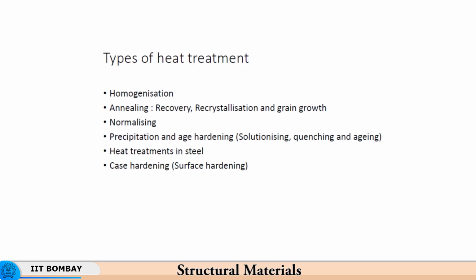So, what people do is, people often work the material using thermomechanical treatment, meaning they roll the material or forge the material, generate a large amount of dislocation density in the material, and then they put it for annealing. So, there what happens is that when the dislocation density is very high, then there are a large number of nuclei for new crystals to form.